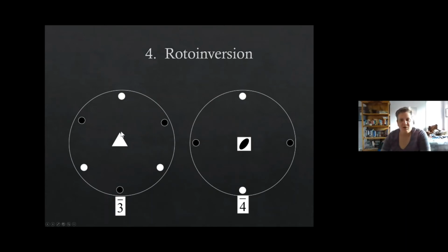Any time that you have one of these symmetry elements, you have to follow it through and produce atoms or molecules at every single point until you get back to the beginning one. That's how you wind up with all the atoms in that mineral. If you just did it once, so if I take this one, rotate 120 degrees, I'm only going to get 2 points, but you have to follow it all the way through to when you get back to the original point. That way you're going to get all the atoms related to that symmetry element and not just a couple.